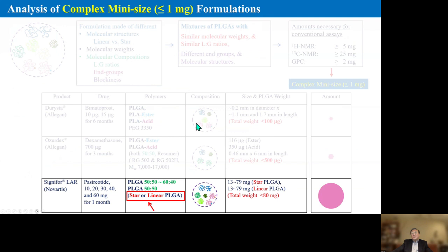Now, let me talk briefly about Signifor LAR. That is, again, not a mini-size formulation, but it has two PLGA. One is star-shaped, the other is linear. And also, both of them have an LG ratio close to 50-50. One is 50-50, the other is between 50-50 and 60-40. Very similar. So our job was to find a way to separate them and quantify them.